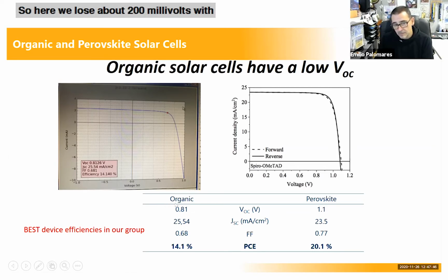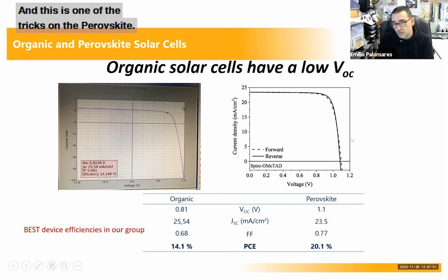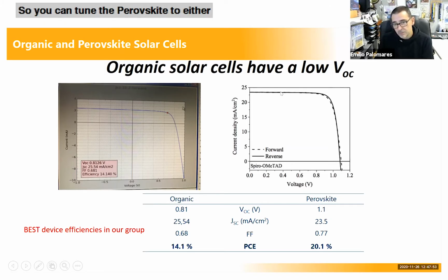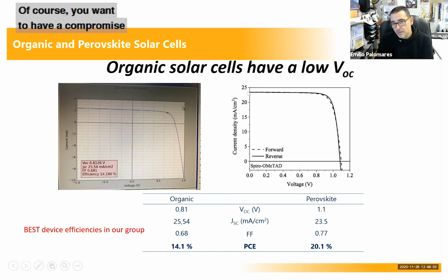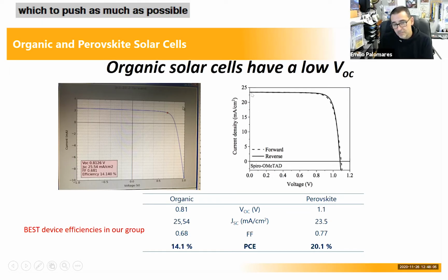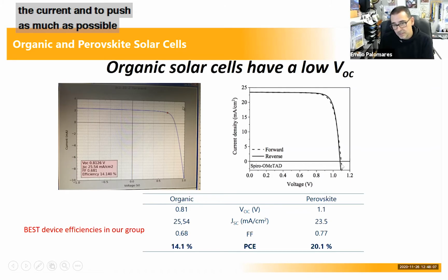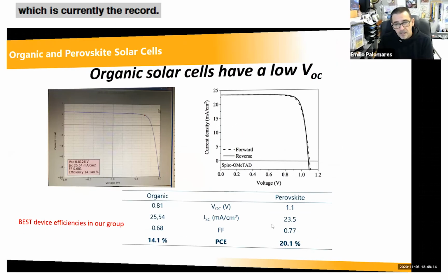So here we lose about 200 millivolts with respect to the perovskite. And this is one of the tricks of the perovskite. So you can tune the perovskite to either go down in current and get higher voltage, or you can tune the perovskite to go high in voltage and lower in current. Of course, you want a compromise, which is to push as much as possible the current and as much as possible the voltage. So, and then you can reach this 25%, which is currently the record.